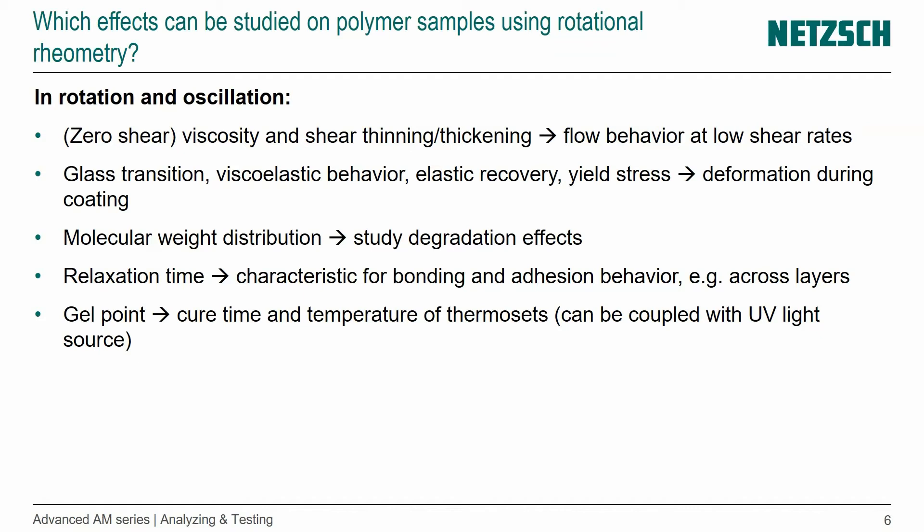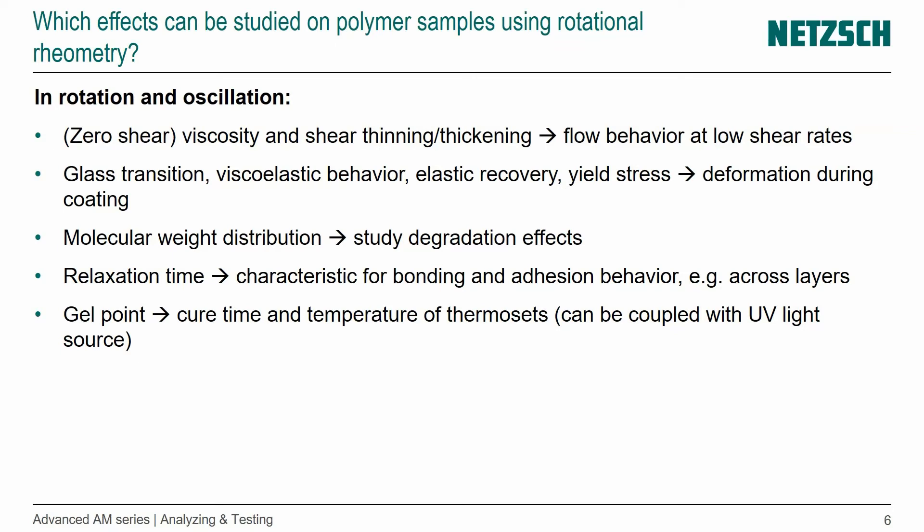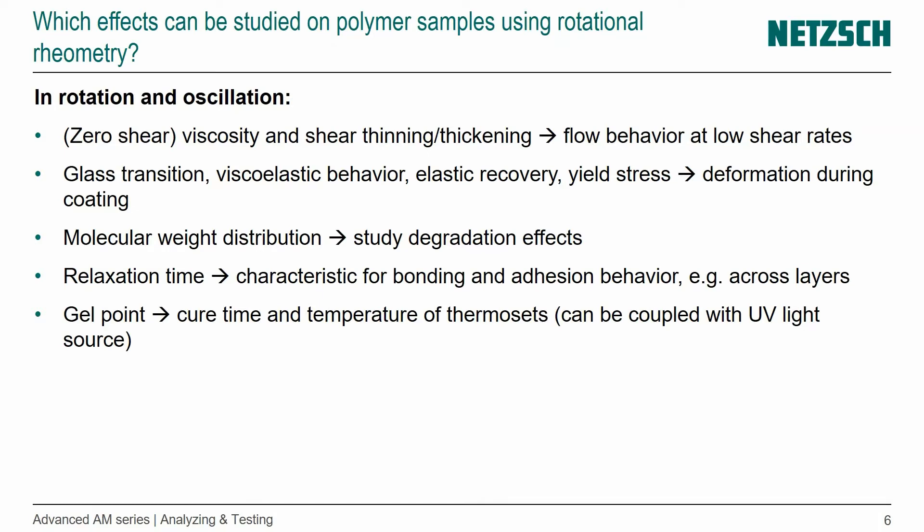We could potentially get the deformation during the coating process. We can study the molecular weight distribution, for example the degradation effects. I mentioned the polycondensation that happens for nylon 12. Rheology is another way to study that. We could study the relaxation time, and that is very important for the bonding or welding that we get between layers, not only for powder bed fusion. That's something that is relevant in almost all of the layer processes.